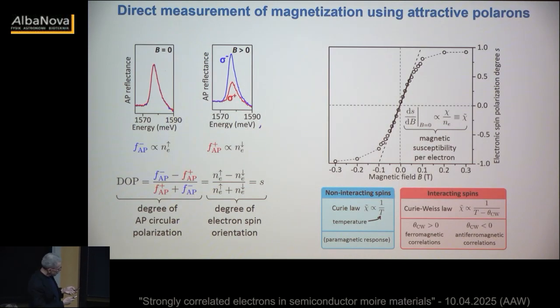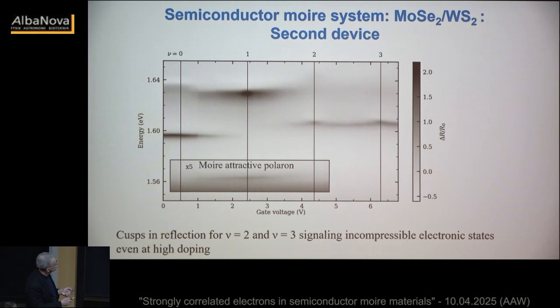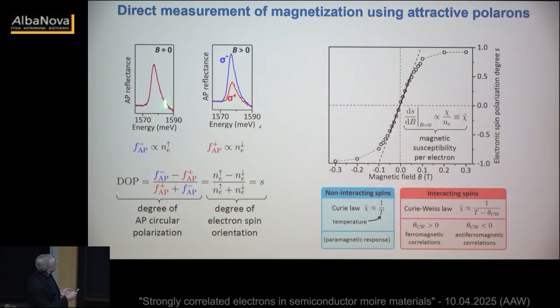So again, we're looking at this moire attractive polaron. And at zero field, sigma plus and sigma minus exactly overlap, which is not surprising, so there is no spontaneous magnetization. If I apply a finite magnetic field, I find that their areas differ. And from this, as I already explained before, I can determine the degree of spin polarization. Now I can measure this as a function of the applied magnetic field, and the derivative gives me the spin susceptibility.